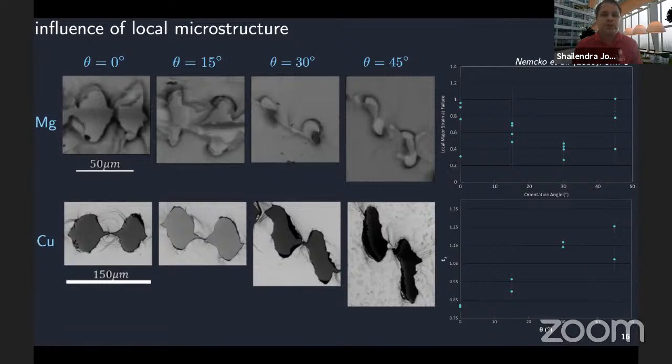But we do observe that once we start with initially oblate voids, the quantitative details are quite distinct from the ones that we observe for spherical voids, but if you are at intermediate oblateness of the void, the qualitative responses are quite similar to the ones that we observe here. Only when you get to sufficiently oblate voids do we start seeing significant repercussions of the sharpness of the void in terms of the qualitative responses.